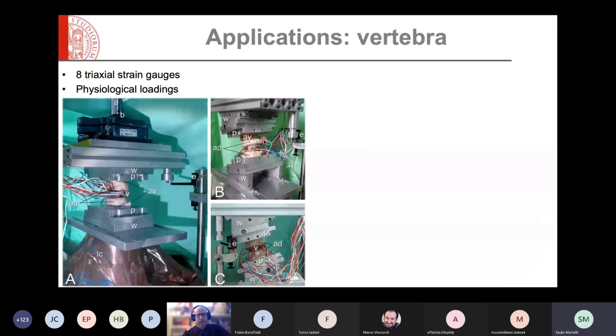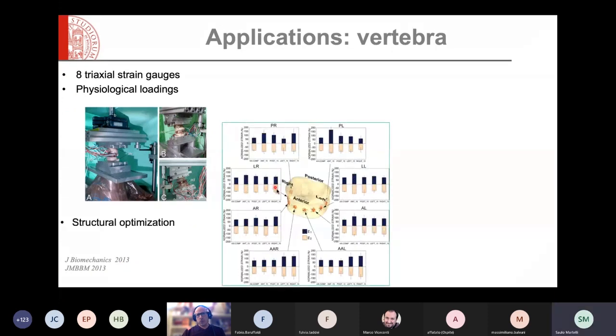We did similar work also in the vertebra, placing as many strain gauges as we could put around the vertebral body. We simulated different loading conditions, axial loading, bending, torsion, and so on. And again, here we observed the structural optimization that led the vertebra to have a quite uniform distribution of strain around the vertebra with a certain loading condition and quite non-uniform for other loading scenarios.